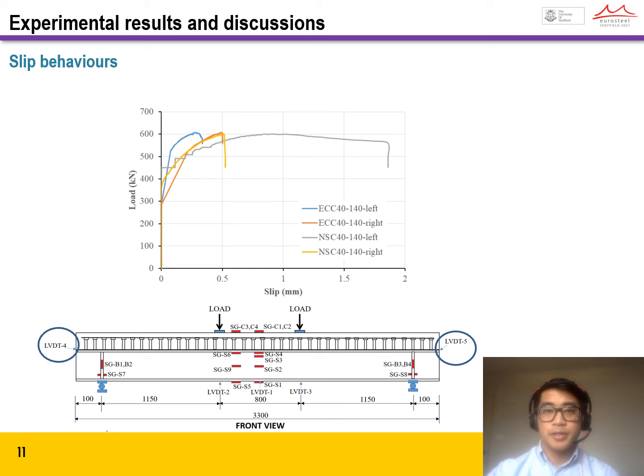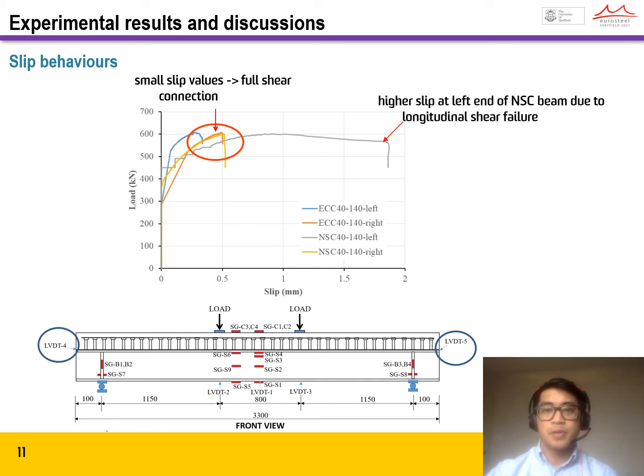The load-slip relationship of the two tested beams was derived and plotted in this figure. The average slip between the ECC or NSC slab and the high-strength steel beam was recorded using LVDT 4 and 5. It was found that the average slip of both beams was negligible until the load reached approximately 400 kN. Afterwards, slip increased to around 0.5 mm at peak load, which is relatively small. Slip at the left end of the NSC beam is higher since this beam was subjected to the longitudinal shear failure.